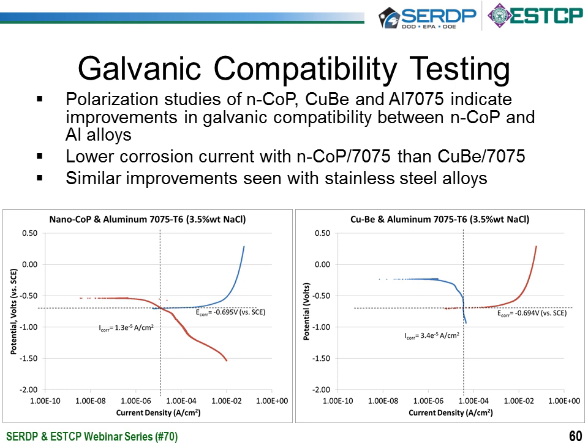In terms of galvanic compatibility testing, we've done some polarization studies of the nano cobalt phosphorus, the copper beryllium, and the aluminum 7075 alloy, a common aircraft alloy, indicating some slight improvement in compatibility between the two. If you look at the polarization curves there, I should mention that when we're putting these dissimilar metals together, the aluminum will generally act as the anode, and the bushing material typically as the cathode.